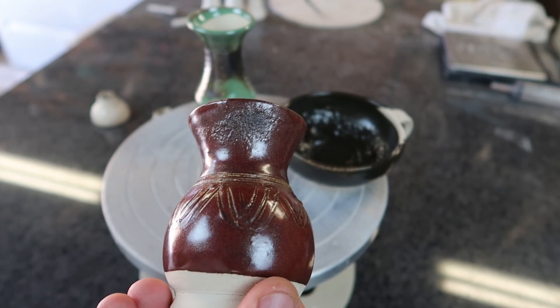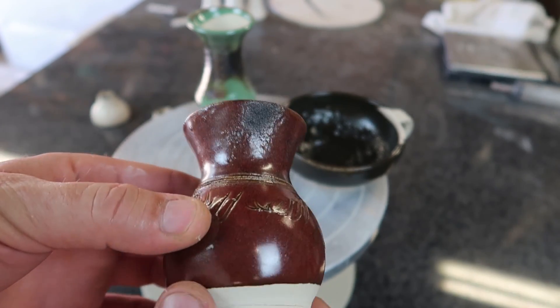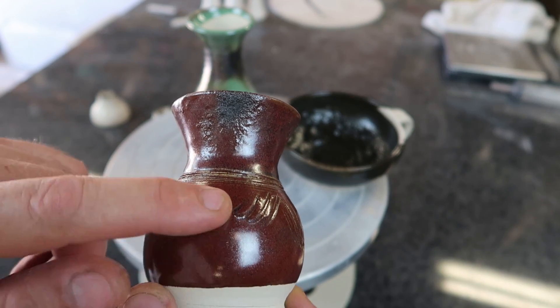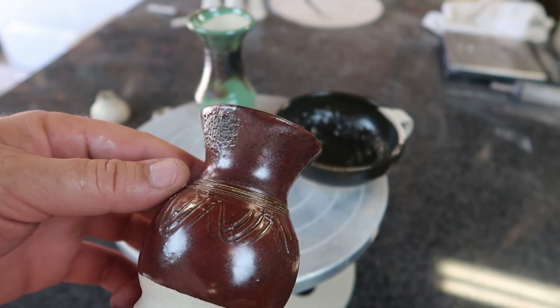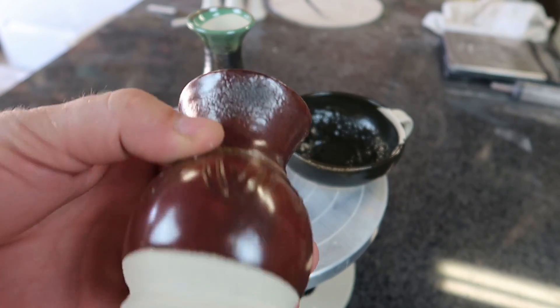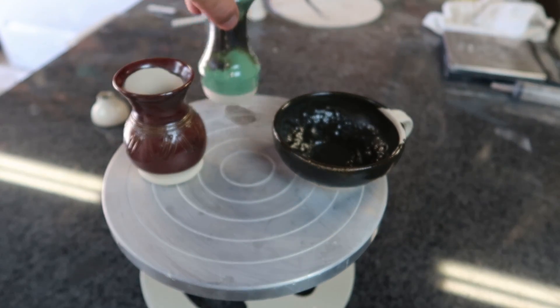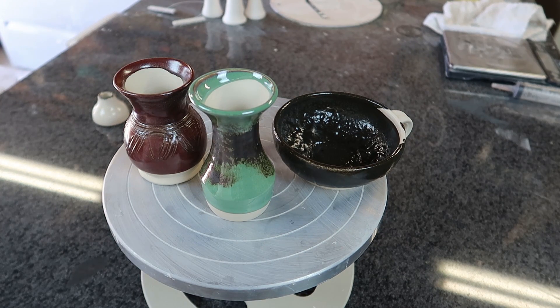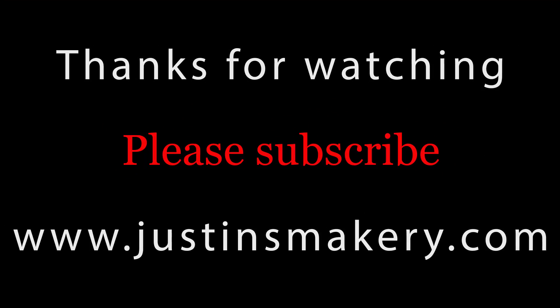The Bailey's red is not as dramatic of a color shift — there's already a ton of red iron oxide in that recipe, so it doesn't blow my mind. But it tells me that firing steel wool and grinding it up is a viable homemade alternative for some sort of red iron oxide for your glazes. So there you go.